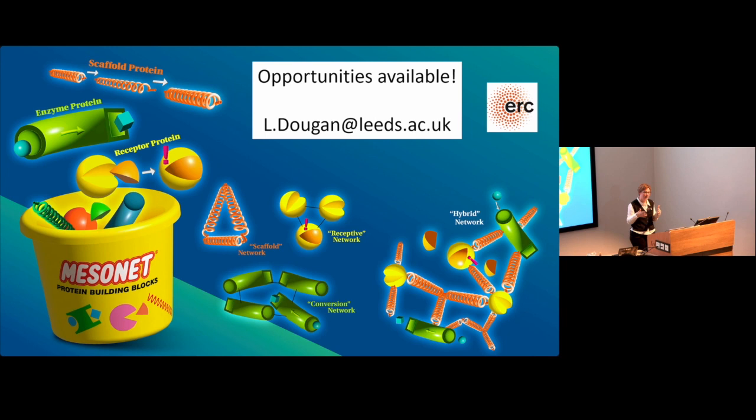And so that's a little bit like the double network hydrogel community, if people are familiar with that. But in that case, you've got one network and another one built on top of it. By using a heteropolyprotein, your building block itself can offer that dual mechanical response. So you can have a bit of a sacrificial lamb within your construct to respond very quickly to force. But then you still have the integrity of that second component that will remain folded. Yep. Okay, one more question here.